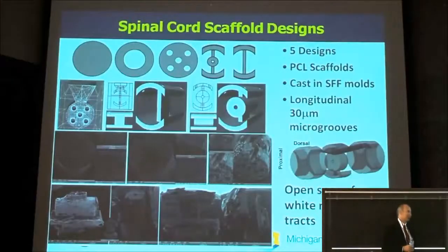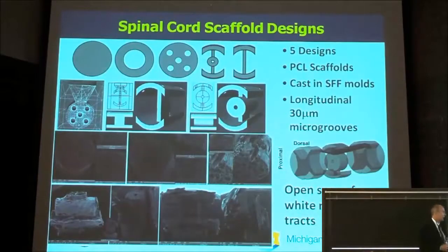Another application, spinal cord injury. So this is a transected rat model. Again, looking at different architecture designs of the scaffold, putting it in a 3 millimeter defect in the rat transected spinal cord. And these gray areas here are not blocked off, but they're actually a sponge material. So again, this is the idea of combining fabrication processes where we make a design structure, but inside that design, there's a sponge. And we put these in the defects.